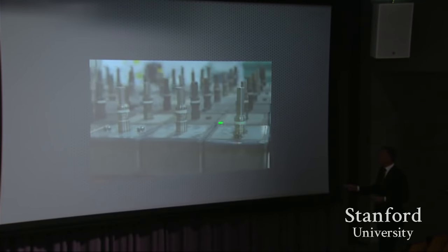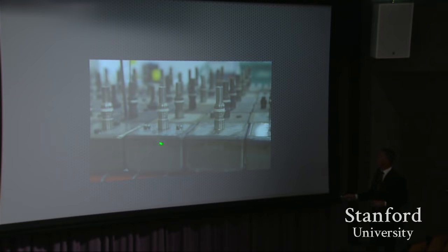This is a 10-centimeter, 4-inch square. And the can is positive. It's just a steel can. This is a TIG weld. It's really primitive. And then there's a feed-through here to make connection to the upper electrode. And right here has a dielectric seal. It's got to be hermetic, dielectric, and it has to stand up to the most vicious metals from the northwest part of the periodic table, magnesium, lithium, and so on. And that's taken us several years to solve, and we've solved it.